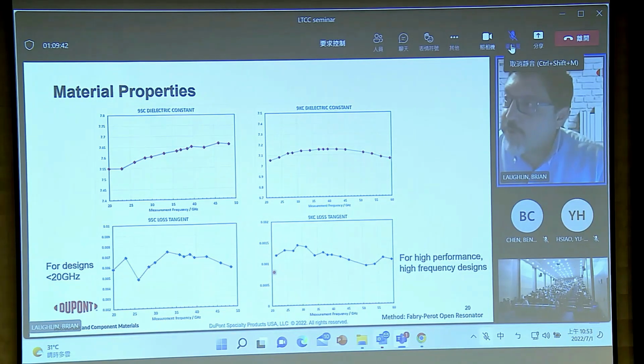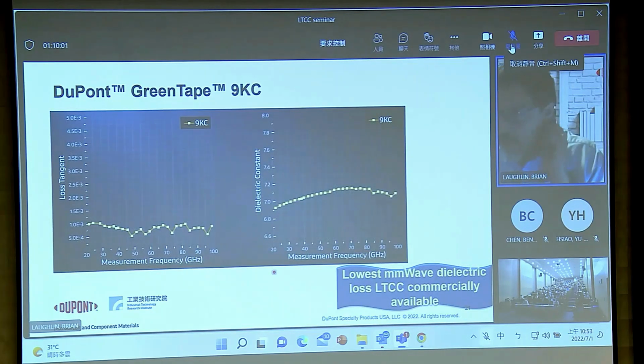But if you have a really high frequency, high performance design, we recommend 9KC. So again, the dielectric constant is very stable over a large frequency regime, and the dielectric loss is 6 times better. And it's a very good dielectric loss that stays low even up through high frequency. And just to drive that point further with 9KC, if we go through an even wider frequency analysis, you can see on the left, the loss tangent stays below 0.001 all the way up through 100 gigahertz. And the dielectric constant is stable through that whole regime.